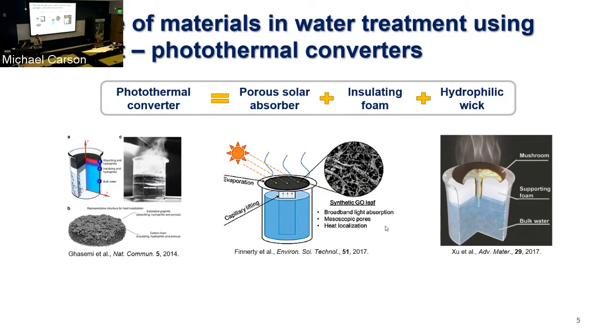and you can see generally what they comprise of are a porous material that's a very strong absorber of solar energy. A lot of times these are carbon-based porous materials or graphite, graphene oxide based. And then you need an insulating foam, which in many cases is a polymeric foam. The reason for the insulating foam is really just to separate that top surface from the bulk of the liquid itself. And finally, you need a hydrophilic material that's going to transport water from the bulk to the surface where evaporation occurs. So this is how you would design a photothermal converter.